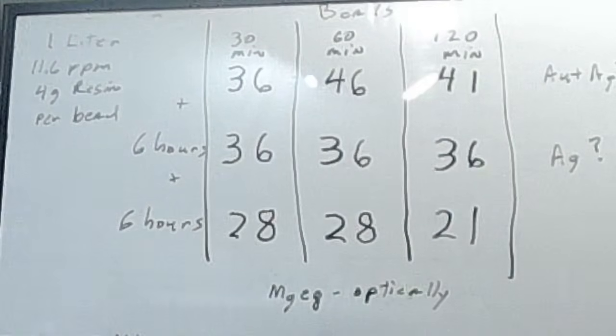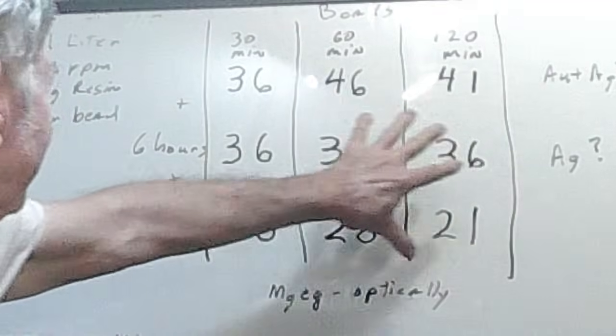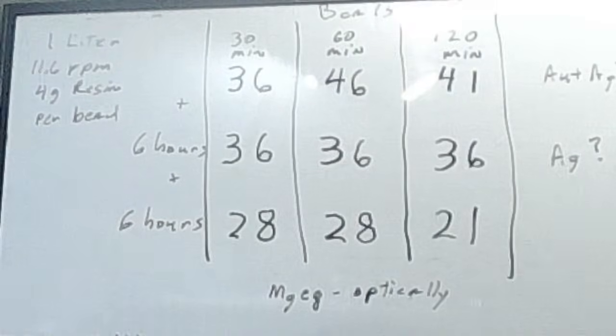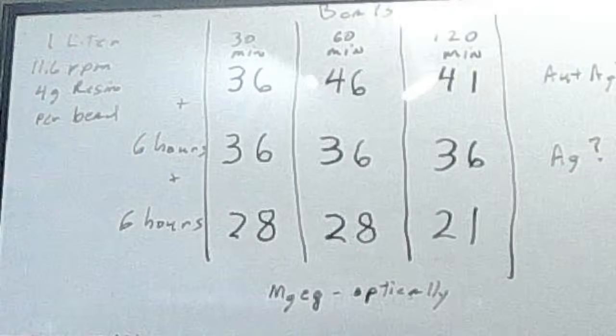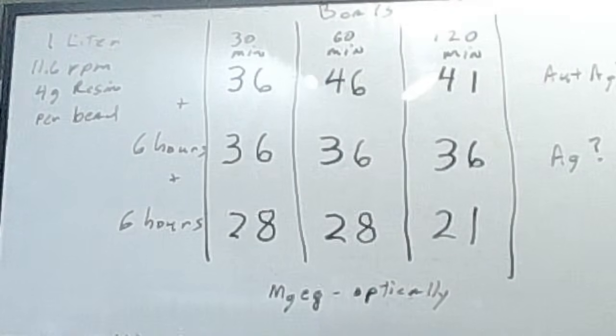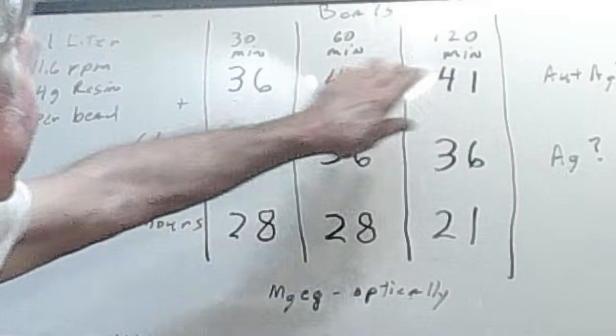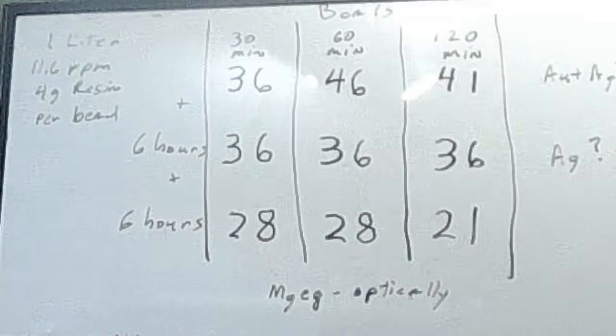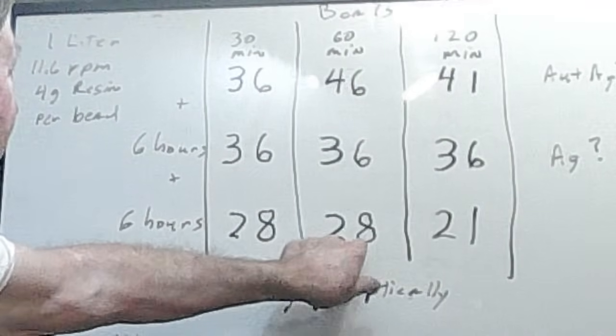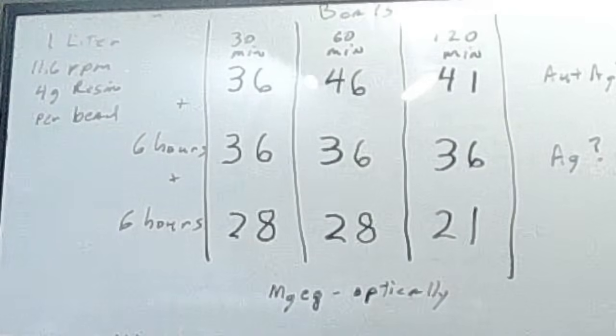And so this is probably mainly silver in here. I'm going to have to take this bead here and test it also in nitric. But what appears to be going is most of the gold is coming out fairly quickly, but even down here, there's a significant amount of it.